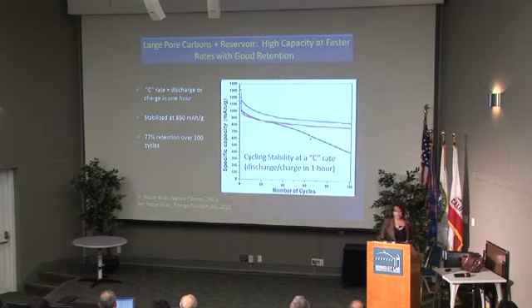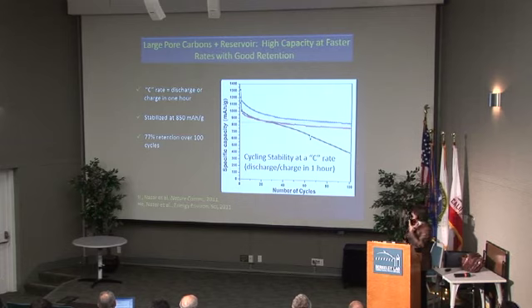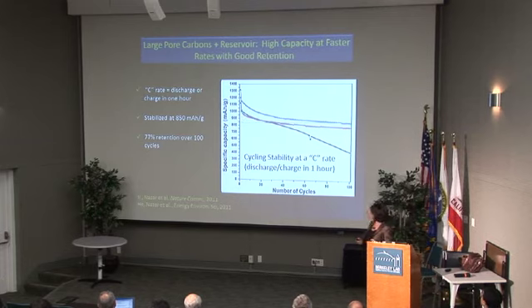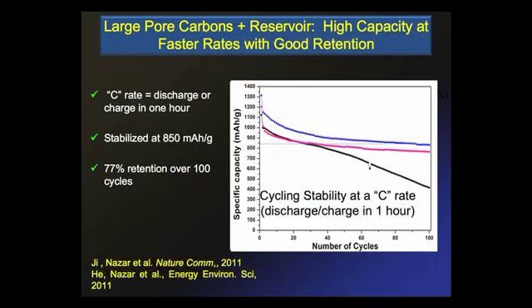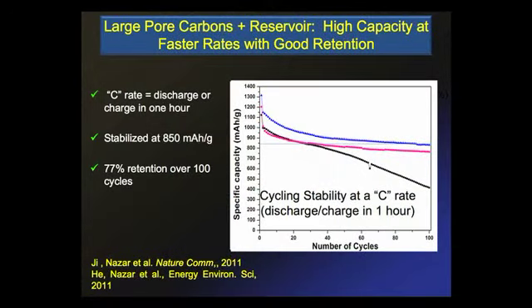So this shows the most recent data that we've had, which does not incorporate SBA15, but it's the same principle, just a different porous material. We're able to sustain about 850 milliamp hours per gram over 100 cycles, and that accounts for about 77% retention. We've also been looking at bimodal systems, and that's reported in this Energy and Environmental Science paper that I don't have time to describe. So this is data as a function of C rate. The difference between the red and the blue is just different porous materials. It's a proof of concept, and this is without the additive in black. So you can see the effect fairly clearly.